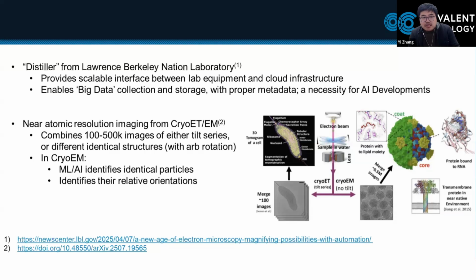the signal strength. And once the lamella is prepared, we can measure its thickness using EELS. And with the sample thickness, the density and the tilt, we can apply absorption corrections, which is, I think, critical for the accurate quantification. And another key step is to calibrate the K factors. Usually the EDS software will provide default K factors, but using the default K factors is usually not enough because the detector efficiency and the geometry will all change the results. So at Covalent, we use either standard samples or IBS measurements to calibrate the K factor. So it will make sure that we get the most reliable and accurate quantitative data.